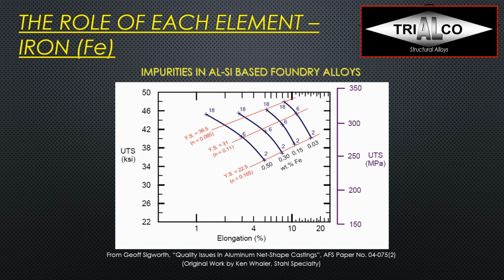And we can see that already a reduction to 0.30 moves the curve quite a bit. And then we see another nice move going to 0.15, and then another big move going to 0.03% iron in the same type of alloy.